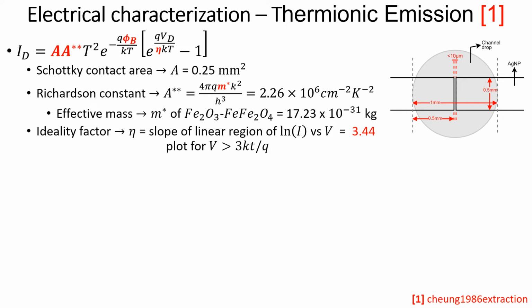Eta refers to the ideality factor, and it is relatively easy to compute as we just require to extract the linear region of the ln I versus V graph, and from that the slope of the graph gives us the value of eta.